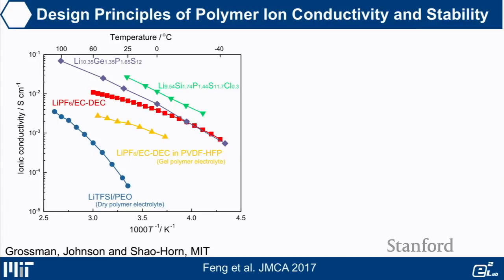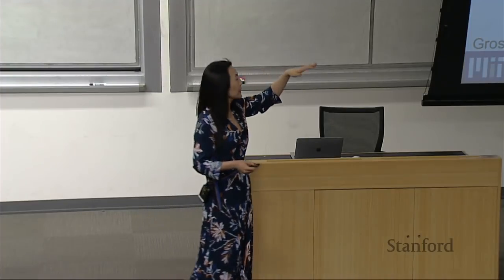Unfortunately, polymer electrolytes are very poor conductors of lithium ion, right? So you can see from this graph, on top are either solid-state ceramic electrolytes or liquid electrolytes. And then the blue dots are polymer electrolytes, or the best polymer electrolytes we've got. You can see that at or near room temperature, we're at least 2 orders of magnitude lower, right? So this is one area that we're working on, right?